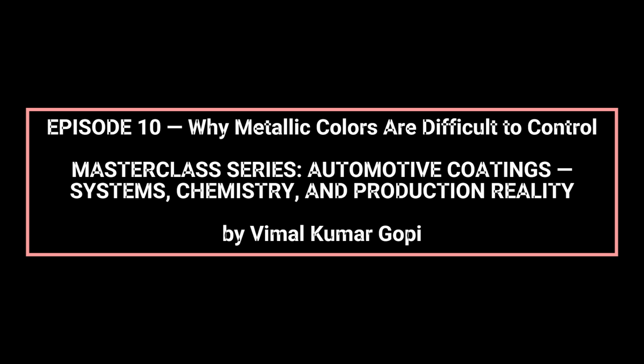Rheology design further complicates metallic control. Low shear viscosity and yield stress influence flake settling and mobility after application, while high shear viscosity controls atomization and initial flake distribution. If rheology collapses too quickly during flash-off, flakes freeze prematurely. If it remains too low for too long, gravitational and surface-driven flow distort orientation.